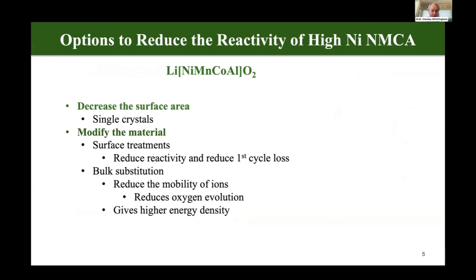We can decrease the surface area, for example, going to single crystals. We can modify the material, both the surface, to reduce the reactivity. And it turns out this also reduces the first cycle loss, and I'll describe that in a moment. Or we can do bulk substitution, which reduces the mobility of the ions in the bulk of the material, which in turn reduces the oxygen evolution. And this will give us then a higher energy density.